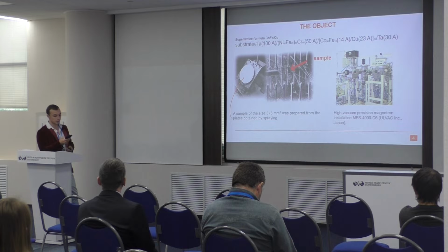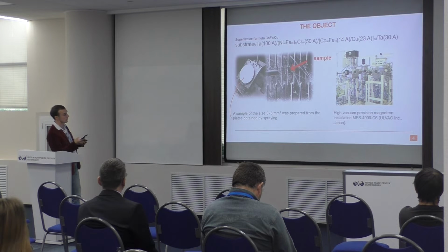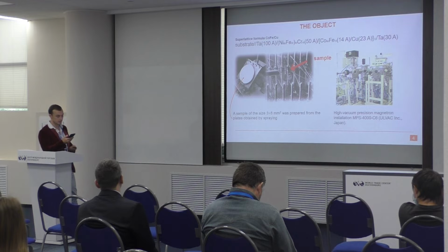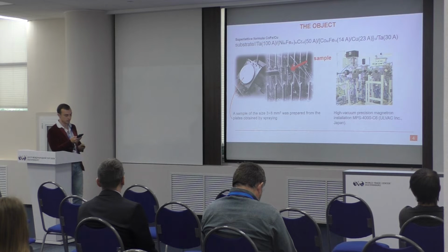The multilayer magnetic nanoheterostructures of cobalt, iron, copper were obtained at a high vacuum sputtering plant manufactured by ULVAC, Japan. The installation uses the method of magnetron sputtering at direct current to spray thin films of magnetic and non-magnetic metals on a substrate in various combinations.